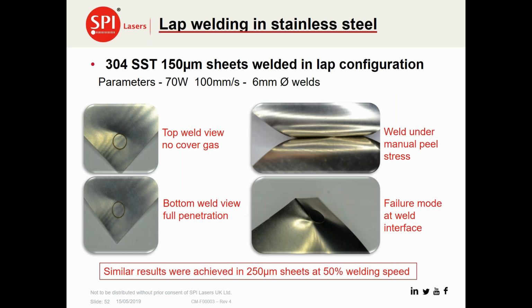This is the same weld, for example, the 150 micron sheets lap welded together, again stainless steel to stainless steel, showing the top and the bottom of the weld in this case, and its deformation under peel. We actually find that the material itself gives up before the weld does. We had similar results achieved in thicker sheets, up to 250 micron, which was at 50% of the welding speed in this case.